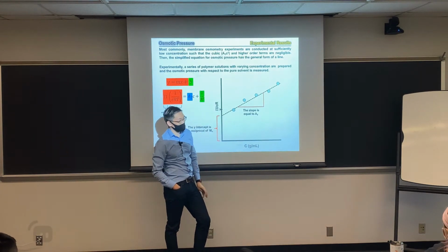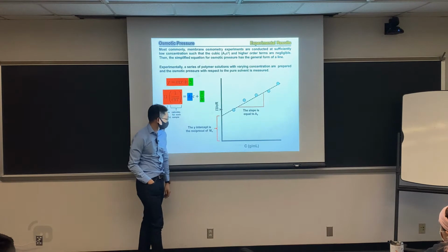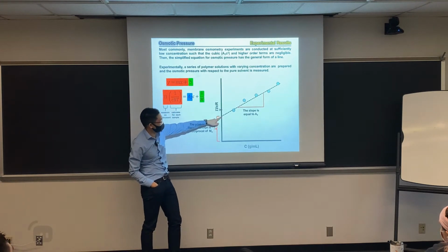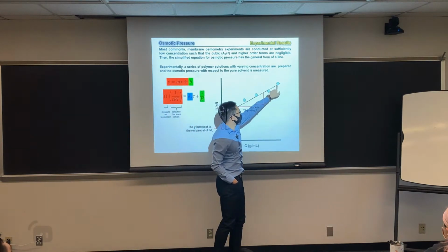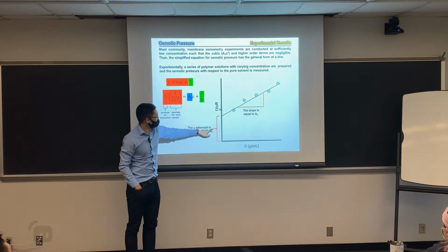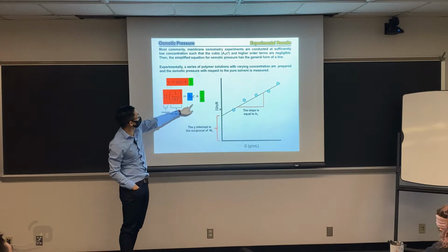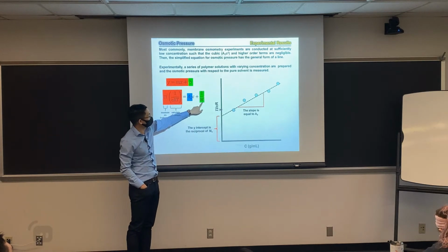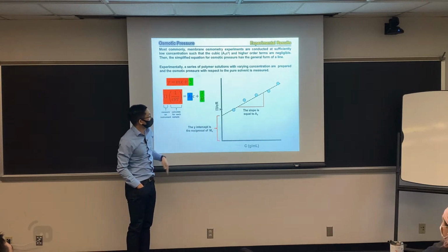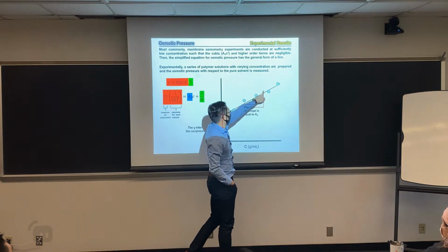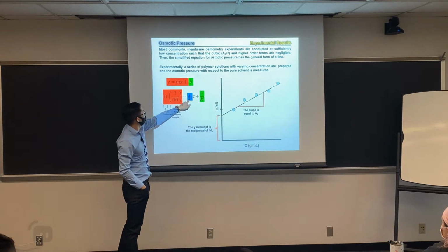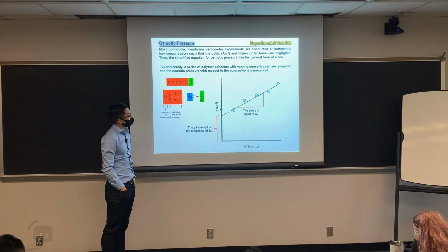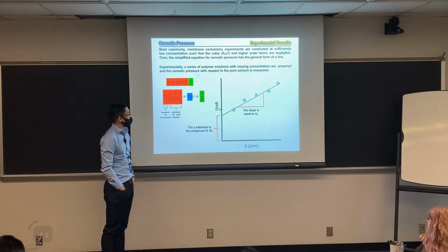And it will give you two interesting, useful parameters. You can measure the intercept with the y-axis. These are your measurement data points. You can get the intercept. The intercept will be equal to 1 divided by molecular weight. And the slope is basically the A2 parameter, given here, your second virial coefficient. Okay.